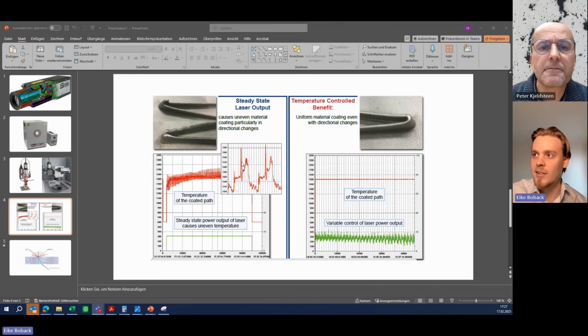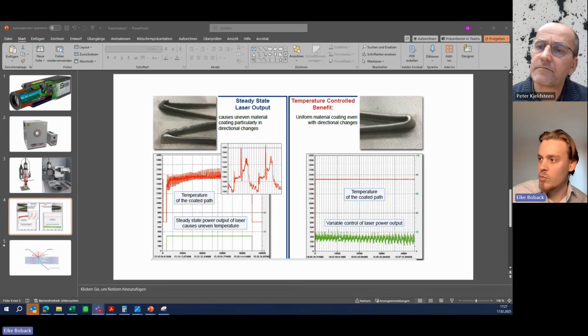And this effect also gives you a bad structure in the material, like some holes and so on. And our approach is to control the laser power, you can see here in green on the right side, and get a constant temperature, and the effects on the material are gone.